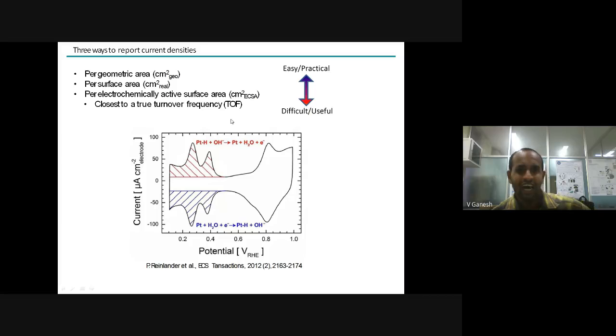Research-wise, you would always like to quantify your parameters. You would like to quantify your catalytic activity by correlating with either the geometric area, the surface area, or the electrochemically active area. The geometric area is a very straightforward measurement. You can measure the geometric area of your catalyst. This surface area normally you would correlate with the BET measurement, right? Brunauer, Emmett, and Teller isotherm-based surface area measurement, but that may not reflect the real active surface area of your electrochemical reaction. So for electrochemical reactions, you need to always correlate your catalytic parameter with the electrochemically active surface area.